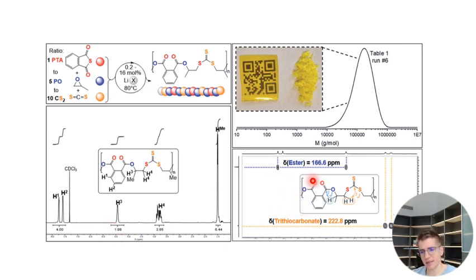And then in the carbon spectrum and in the HMBC that correlated the hydrogen spectrum to the carbonyl resonances here, it became very clear that you got this distinct correlation and signal in the 13C spectrum at 166 ppm very cleanly, which correlates to the ester, and another resonance at 222 ppm, which correlated to the trithiocarbonate, and the CH2 groups here correlated to the trithiocarbonate, whereas the aromatic units as well as the CH groups from this tertiary center here correlated to the ester. So that was relatively clear.